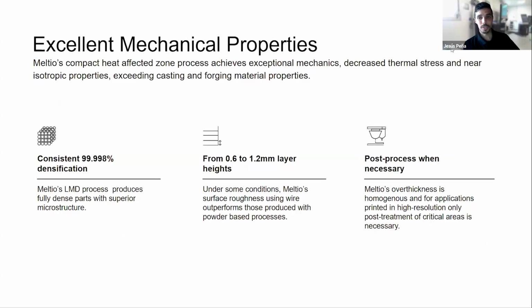Overall, something that we focus pretty much on is those mechanical properties. To achieve them, what we do is make several iterations with the materials we print. So first of all, what we need to do is achieve the fully dense parameters. So we make some testing, we make some iterations until we get this consistent densification of 99.99.